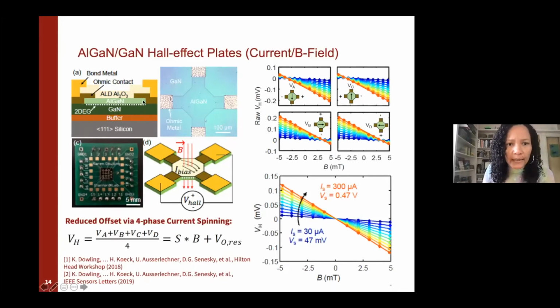So what happens when you make this type of transducer, as with most sensors, is that you often have these sensor anomalies. One in particular is offset voltage. So what that means is in a zero bias, so when you have zero magnetic field, you actually are getting a voltage that's present, and that's due to anomalies in the sensor design. So this is something that you want to cancel out. And so we do that at the circuit level. We utilize something called current spinning, where we're basically averaging the Hall voltage using these four contacts, and then also changing the direction of our applied field. We can average that out, and then now in a zero magnetic field, we can have a zero crossing, relatively. So there's still some offset here.